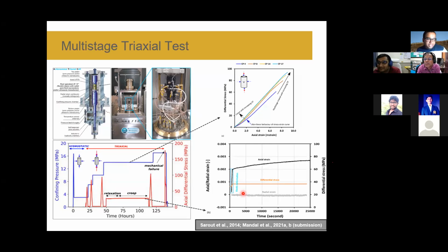Yes, so this is basically a decision we have made. We are going to measure for 6 hours because at 6 or 8 o'clock we stop recording and leave it overnight, so that we get 6 hours of time to relax. But people have done this for scenarios starting from 2 weeks, 4 weeks, and probably they don't see much variation whether you measure for 8 hours or for 3 days or 4 days.